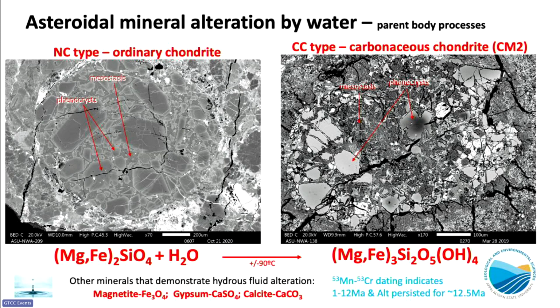In most stony meteorites, we find metal grains composed of iron-nickel alloys. If we subject those to some oxidation reactions during hydration, we form the mineral magnetite. We can also form precipitate minerals like gypsum and calcite. Again, we can use that relative age dating technique using the manganese chromium system that indicates that this process happened between 1 and 12 million years after the formation of CAIs, and it persisted for about 12.5 million years.